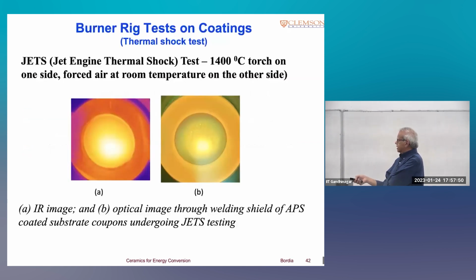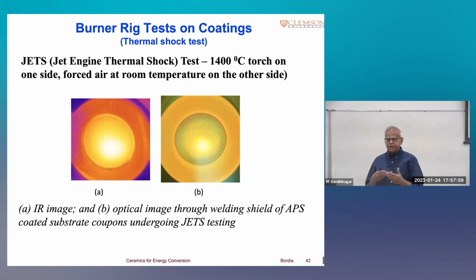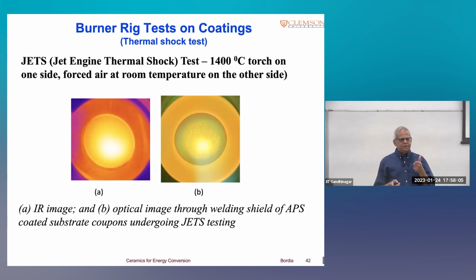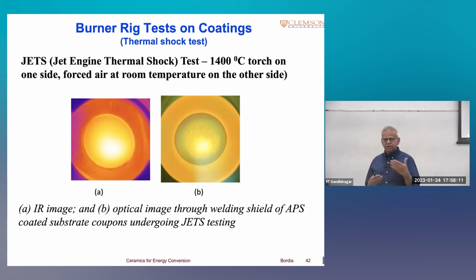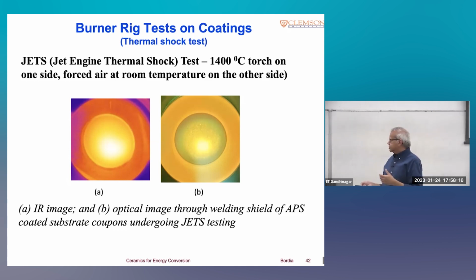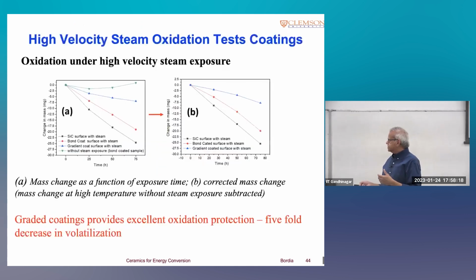This was in collaboration with GE, and they took our coatings that we put on the silicon carbide and tested them in these very extreme thermal shock kind of setting, where essentially on one side, you have a fuel torch, which was at a temperature of 1400 degrees C. And on the other side, you have just cold air. So it's an extreme thermal shock, and these coatings survived these tests.